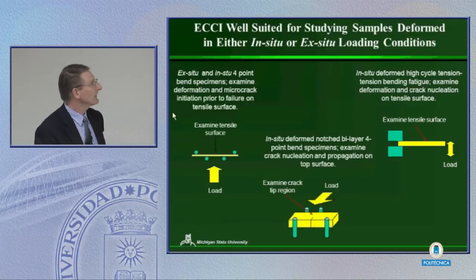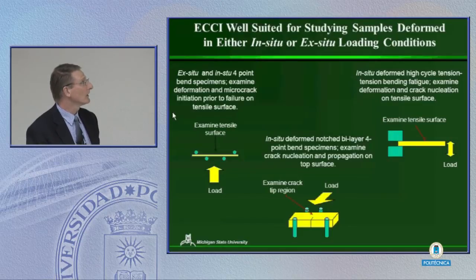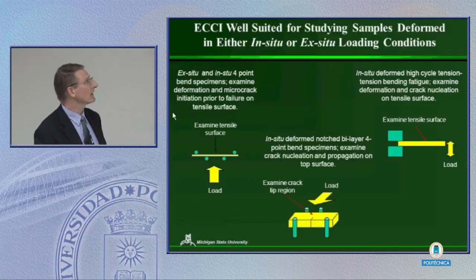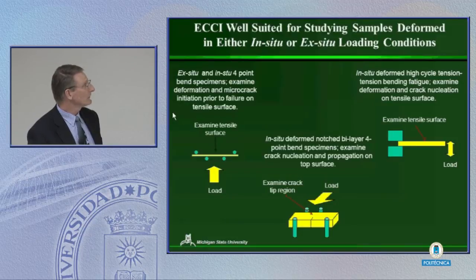Given that, this technique, electron channeling contrast imaging, is really very well suited, particularly for in situ experiments. Now what I'm going to go through is I'll show you some things from both in situ and ex situ experiments. We can do both in situ or ex situ 4-point bending. The advantage here with 4-point bending is we can look at the tensile surface of the sample where the maximum stress is. And that really helps us work our way through some things.